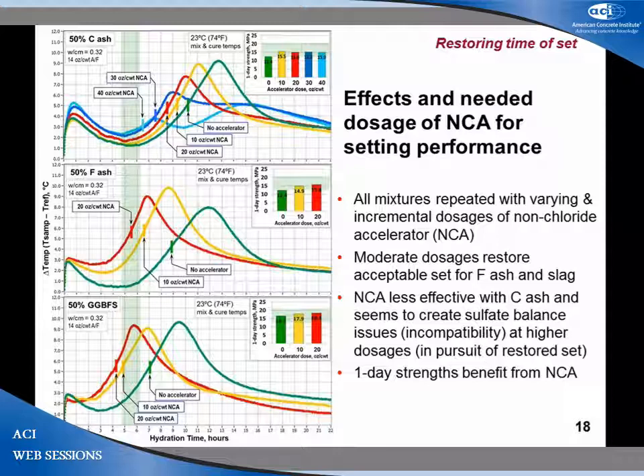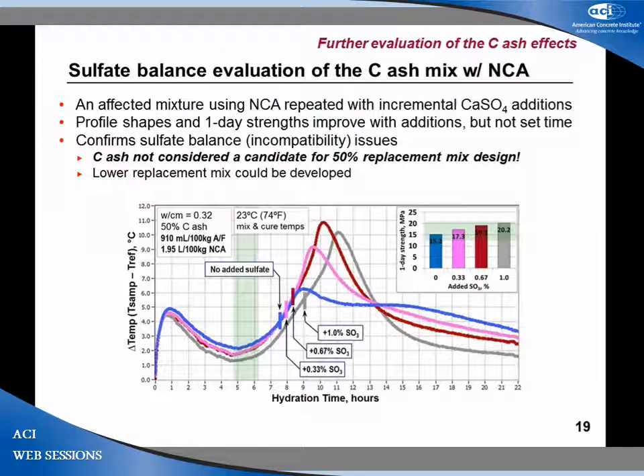And as we increase the accelerator dosage, we're beginning to see some misshapen curves. We're not regaining much one-day strength. One-day strengths are increasing as we accelerate the other ones. So now we are, sure enough, seeing some misbehavior with the C ash mix. If we have questions about that and we want to verify for our own benefit that this is a true incompatibility issue, which is sulfate balance related, then we can actually take the C ash mix and begin to doctor it with sulfate additions. And sure enough, when you do that, you restore normal performance. The strengths begin to rise again. So that confirms to us that, yes, indeed, that was a sulfate balance incompatibility problem for the C ash.